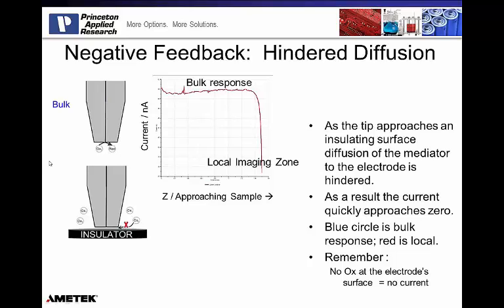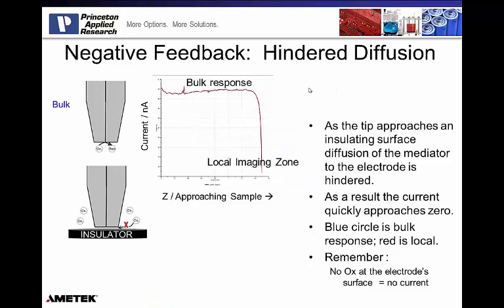So if I look at my image here in the top left, the bulk response, I've drawn out what the SECM probe is going to look like. It's coming down the shaft of the electrode, then it starts to taper in, and then I get down to that flush polished glass and platinum interface at the tip. I'm going to take the potentiostat and polarize it to the level dictated by the cyclic voltammogram. So in my specific example, I've got the iron 3+, and I'm going to polarize the tip to negative 250 millivolts. In a bulk response, that causes the ox, or the iron 3+, when it touches the platinum, to accept the electron and become the reduced species. So that's my iron 3+ to iron 2+ reaction. That causes the current to flow at the 40 nanoamp level for this response.